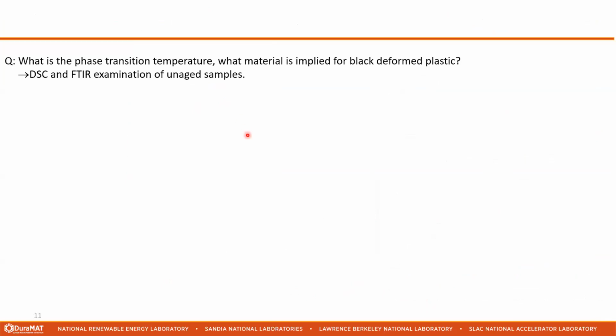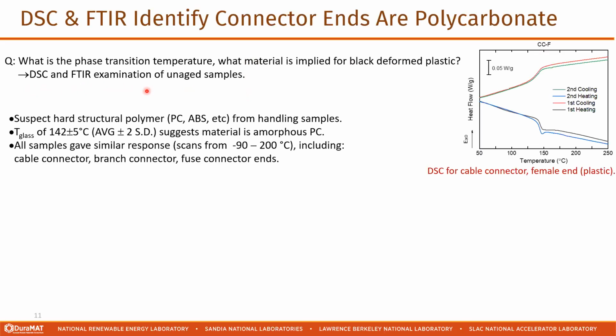So knowing the benchtop results, we wondered what's the phase transition temperature and what material is implied for that black plastic that's used in the components in the sample assembly. And so we used DSC and FTIR characterization on unaged samples. I'll start first with the DSC, and these are the measurements that Sonia helped us with. We suspected this was like a structural polymer just from handling the samples beforehand. And the result here suggests a glass transition temperature on the order of 142 C.